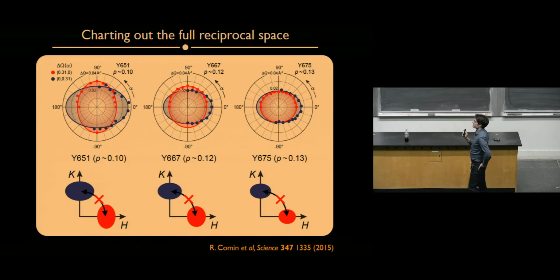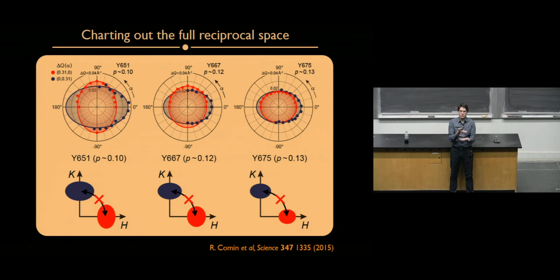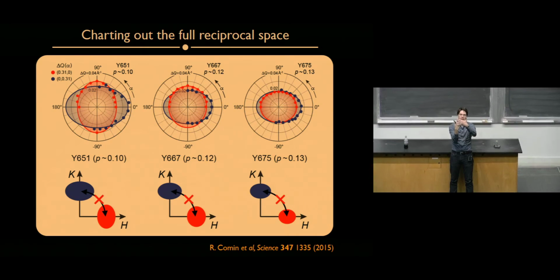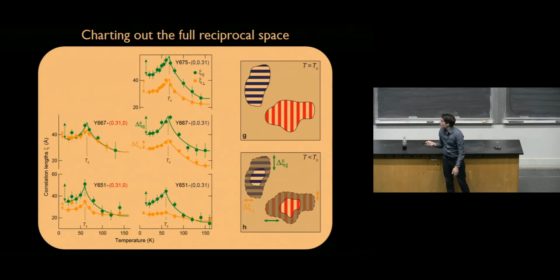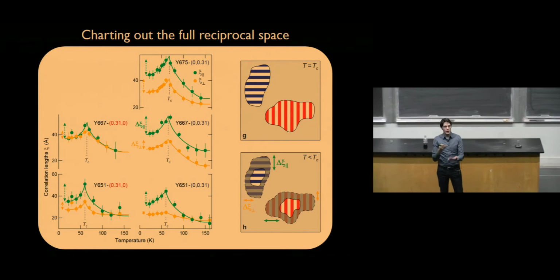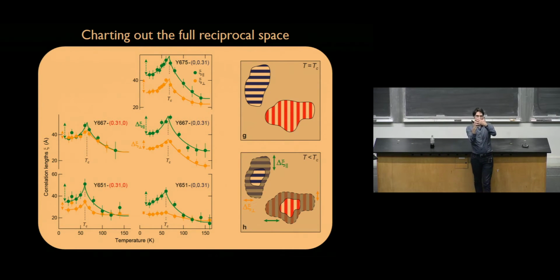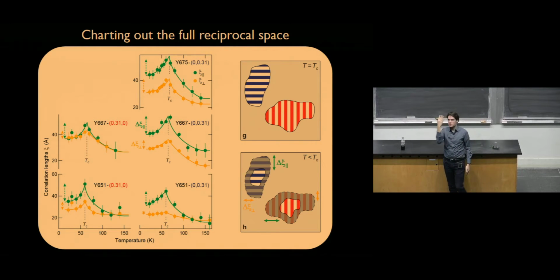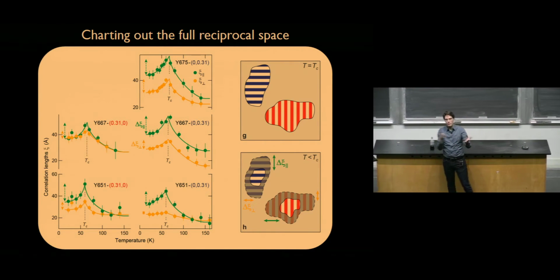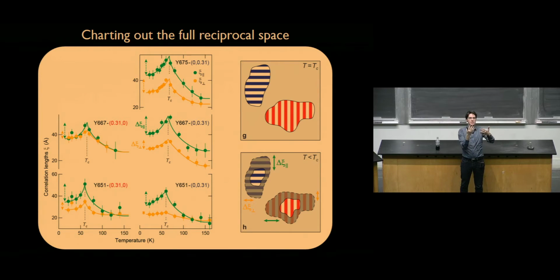So they violate a symmetry which is to be expected if you have two modulations, one along one direction and one along the other direction, present at the same time in the same spatial regions. If that were to be the case, then you would expect these two peaks to have the same structure, but actually they have the opposite structure. As you can see, the anisotropies are pointing along different directions. So this is evidence that actually at the local scale, the order is not bidirectional, but it's unidirectional. So you have stripes at the local scale. Like globally, you have both of them. But at local scales, you have domains.